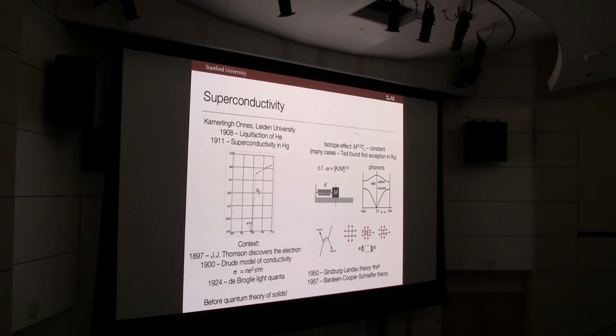So since that discovery, many, many things had to be understood, both theoretically and experimentally. So that's what these three dots stand for. But again, to give you a very terse survey, one of the important experimental aspects that led to a microscopic understanding was that in many superconductors, if you could change the isotope of the elements, you found this relationship that the square root of the mass times Tc is often roughly a constant. It turns out Ted found one of the first exceptions of that in ruthenium.